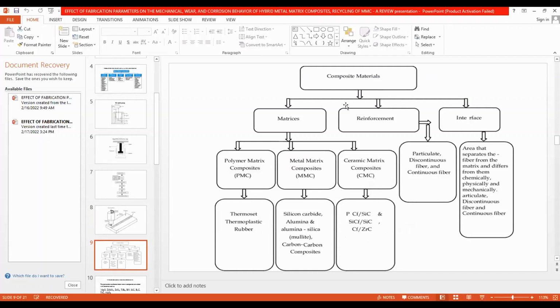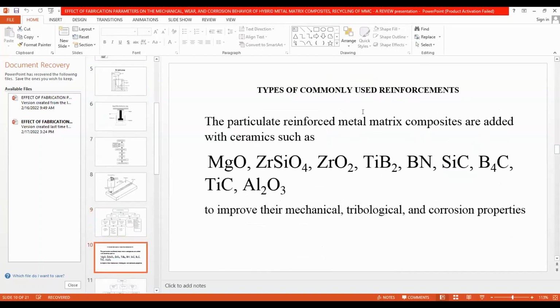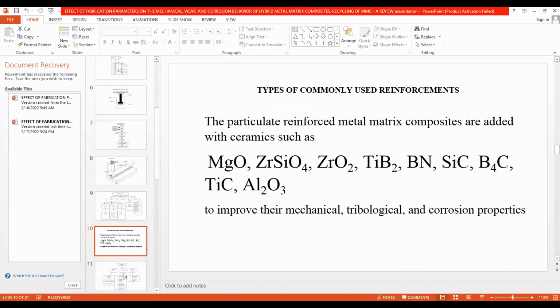Another very important thing is the type of reinforcement that is used. You have alumina, silicon carbide, boron carbide, titanium carbide, tantalum carbide. In other words, a combination of oxides, borides, and carbides are generally used as synthetic reinforcements to improve the strength and other properties like tribological properties and corrosion properties of the metal matrix composites. You have magnesium oxide, zirconium silicate, zirconium oxide, titanium boride, silicon carbide, boron carbide. These are very commonly used synthetic reinforcements.